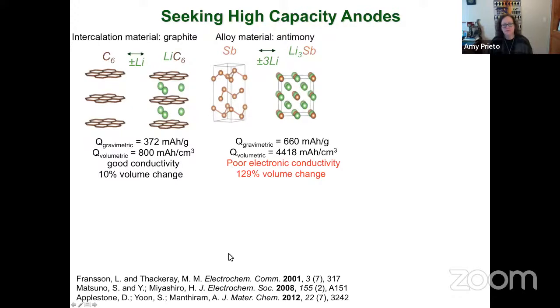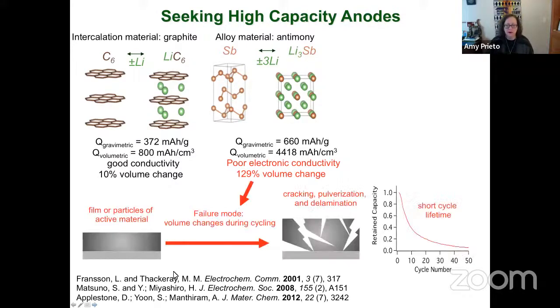If you move to something like antimony, this is very similar to silicon in that it is a conversion alloy material. You're breaking bonds and making a new compound. So in this case, you're making lithium antimonide. The gravimetric and volumetric capacities are significantly higher, but lithium antimonide by itself is a pretty bad semiconductor, so the electronic conductivity is fairly low, and the volume change is pretty significant. The problem there, again, because we're not using binders, is we electrodeposit a dense film. And if you cycle that many times, because of the volume expansion, the anode will crack and you observe pulverization. That results in a pretty significant drop in retained capacity as a function of cycle number.